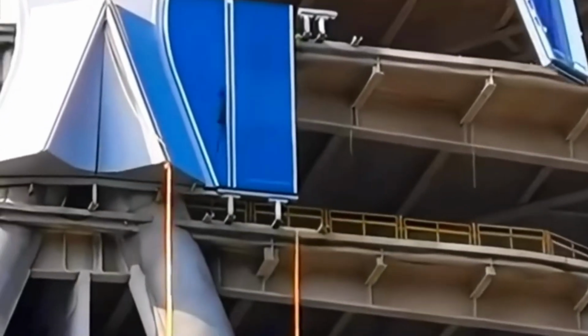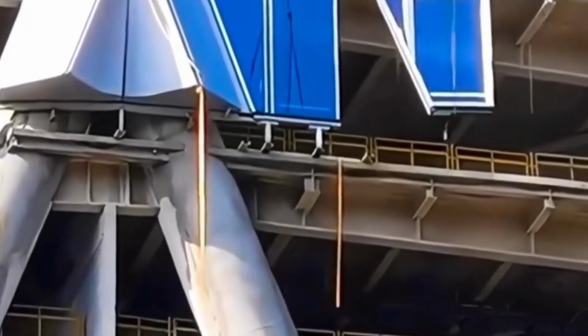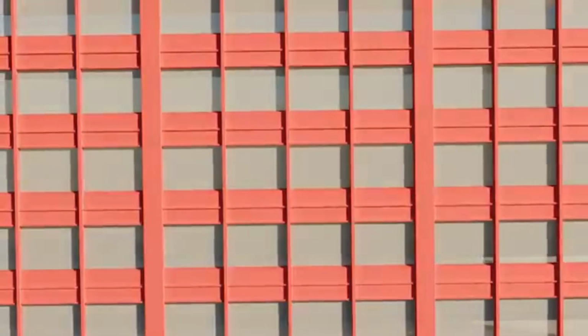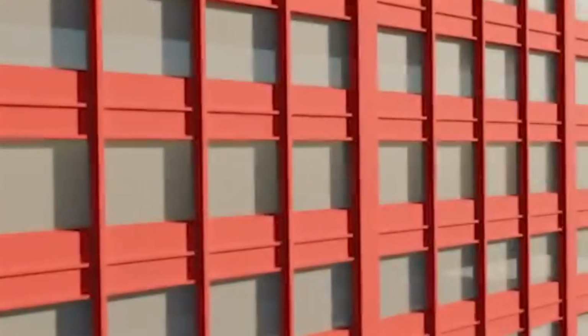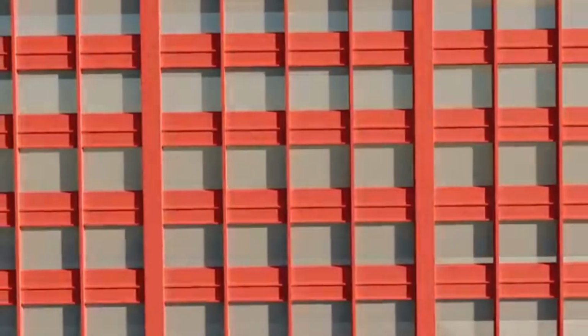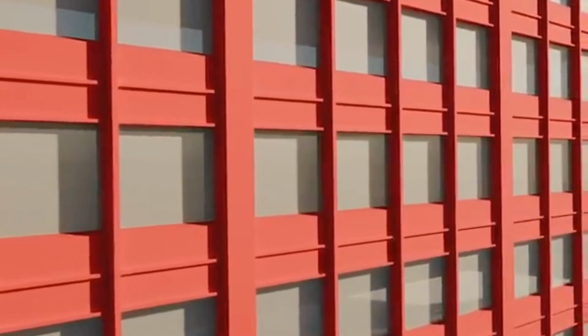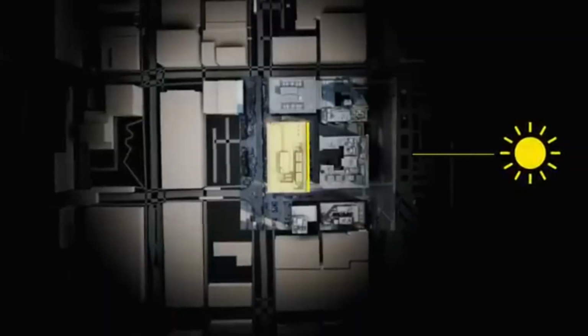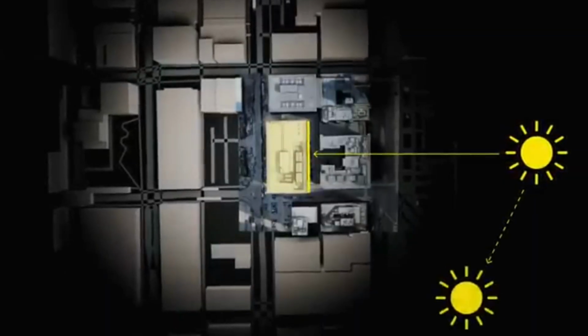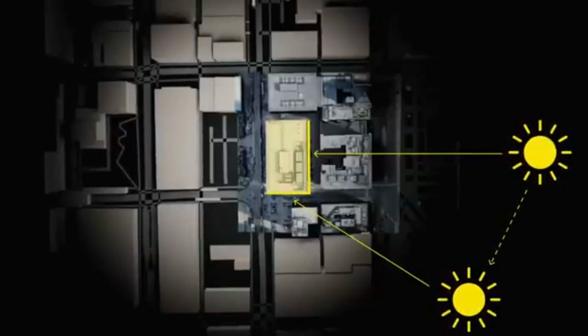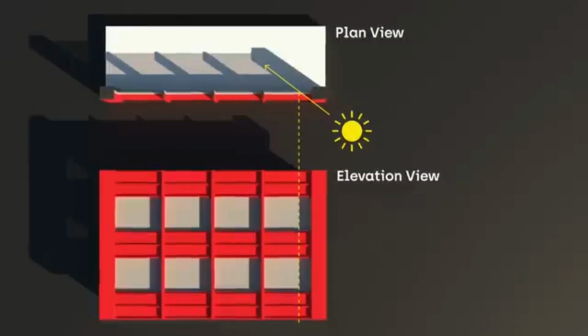Edge damage is actually the most common cause of seemingly spontaneous breakage. Glass is strongest when its edges are pristine, but microscopic chips or nicks during cutting, transportation, or installation create stress concentration points over months or years as the building sways in the wind. As temperatures cycle day to night, these tiny imperfections grow until the glass finally gives way. A pro tip from facade contractors: handle every panel as if it's already installed, and inspect edges under bright light before acceptance. Once installed, you can't fix what you didn't see.